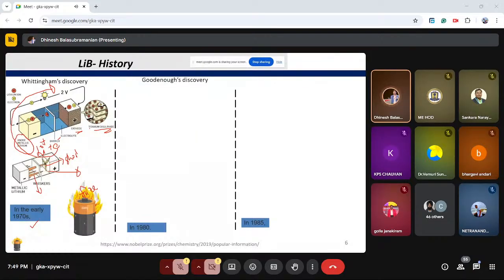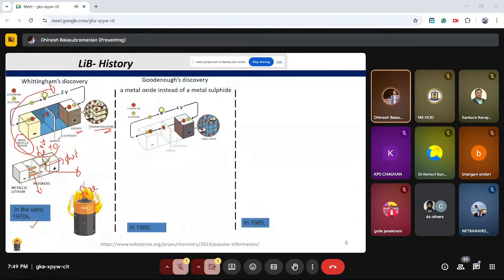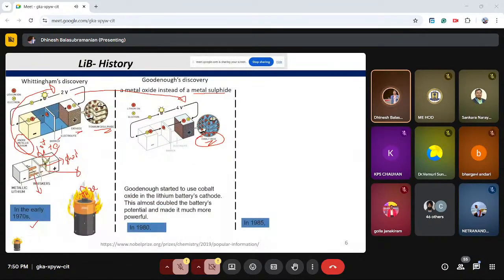And then comes the Goodenough discovery. Instead of making use of titanium disulfide, a metal sulfide, he tried to deal with a metal oxide. He replaced the titanium disulfide with cobalt oxide, and on the other side he dealt with lithium as the base, and it resulted in a higher voltage level, more or less close to the same one as of now. Goodenough started to use cobalt oxide in the lithium battery cathode. This almost doubles the battery potential and made it much more powerful. So that is the great progress from the Whittingham discovery to the Goodenough discovery, where he just changed the cathode material in an effective way.